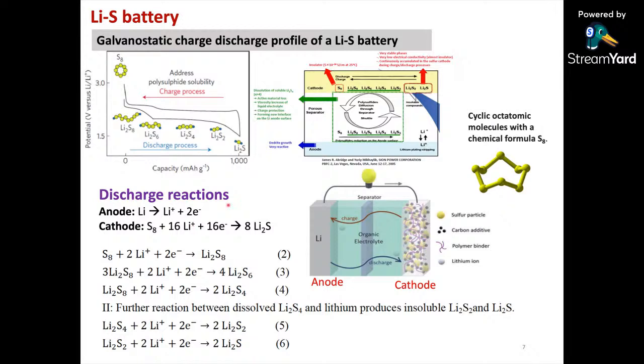So this is the discharge reaction I mentioned. This S8 at the cathode, with lithium plus and electron minus, first forms Li2S8, and then further Li2S6, Li2S4, and these are the higher order polysulfides. They nicely dissolve in the electrolyte, and finally it will form the stable Li2S and Li2S2. Because of the dissolution of sulfur as polysulfides in the electrolyte, the viscosity is going to increase, and we tend to lose the sulfur.